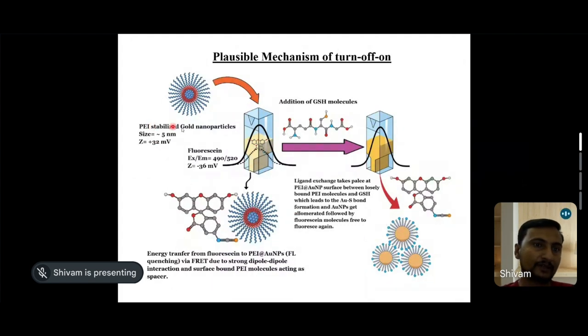Because polyethylenimine stabilized gold nanoparticle was around 5 nanometer in size and had a zeta potential of plus 32 millivolt. Similarly, fluorescein had an excitation emission at 490 to 520 nanometers and zeta potential of minus 36 millivolt. So minus 36 millivolt and plus 32 millivolt promoted a very strong dipole-dipole or electrostatic interaction between the fluorescein molecule and gold nanoparticle, which paved the way for the fluorescein quenching, because the gold nanoparticle is a very good acceptor of the fluorescence emission.